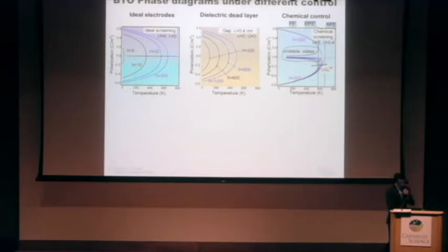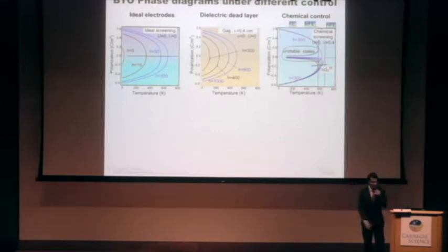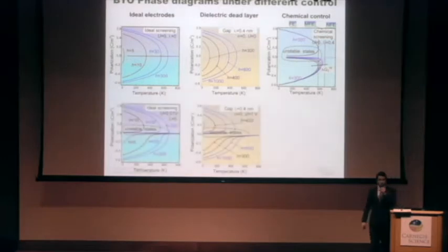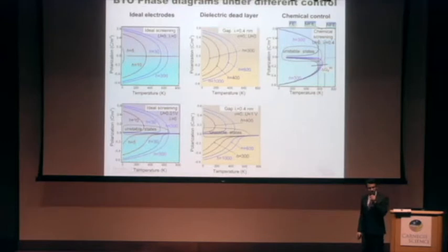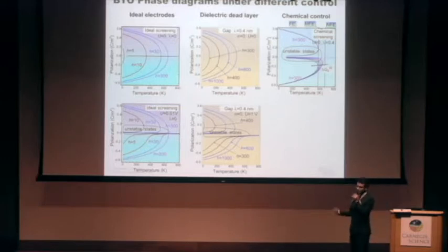But it's a little bit hard for us to physically change these delta G values. Of course, you can't do that because it's given by nature. What you can do is apply a voltage, so apply a potential. Let's see how these phase diagrams change under applied potentials. In this case, again, ideal screening. You simply asymmetrize a double well potential, and you'll stabilize one polarization state over the other.